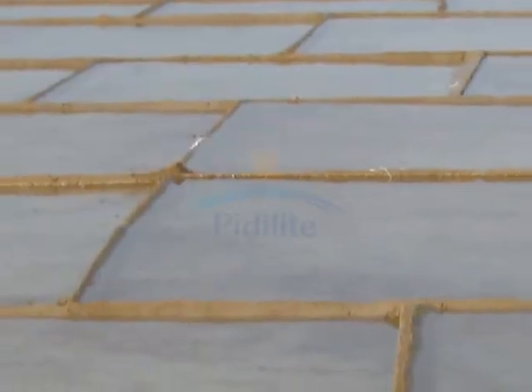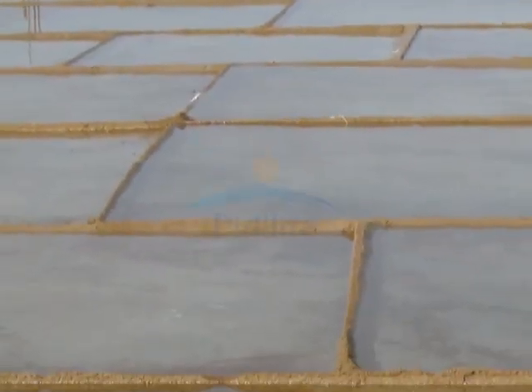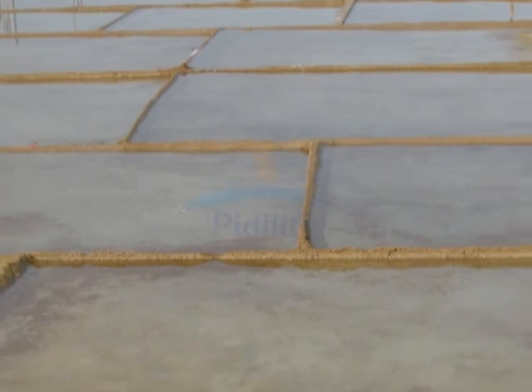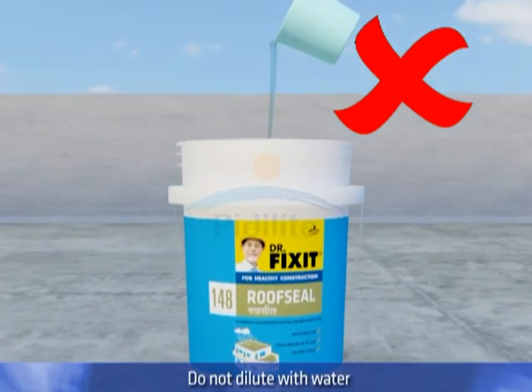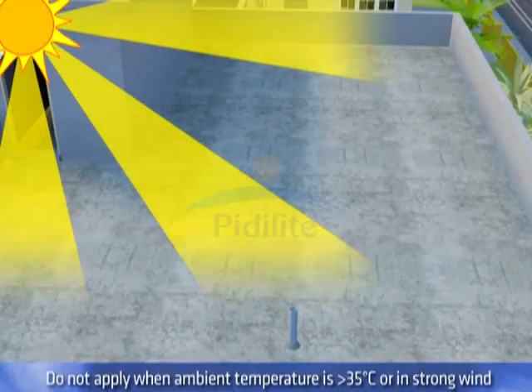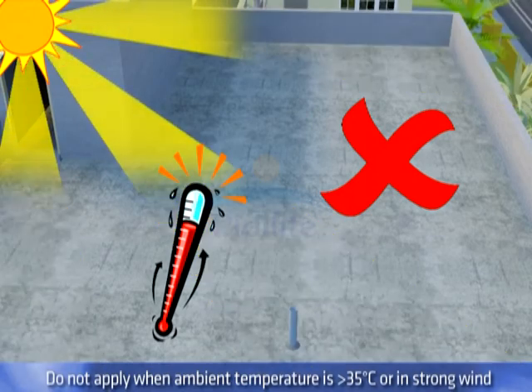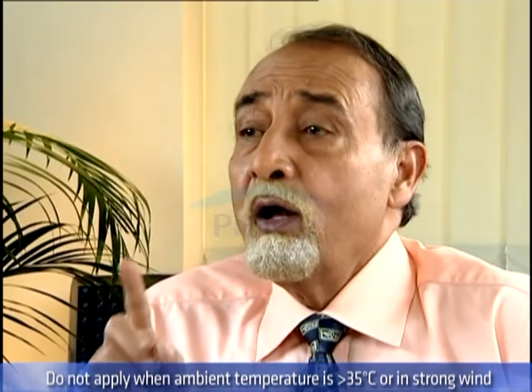Before any waterproofing, allow curing of the slab properly with water in accordance with good curing practices. Do not dilute roof seal with water. Do not apply roof seal when the ambient temperature is greater than 35 degrees Celsius or when the wind is strong, because the surface of the film will dry fast and prevent evaporation of the underneath surface. This may lead to blisters.